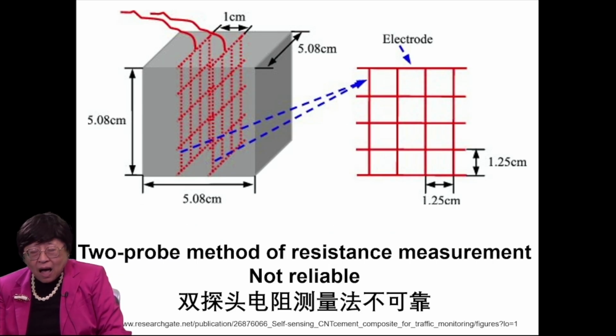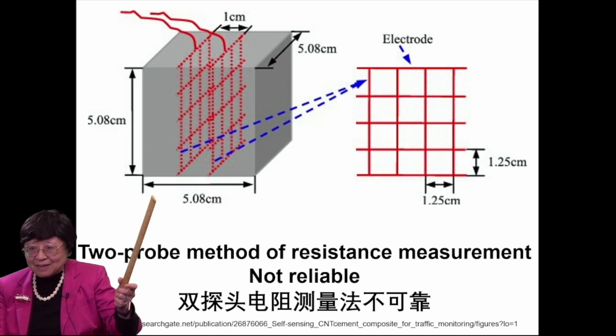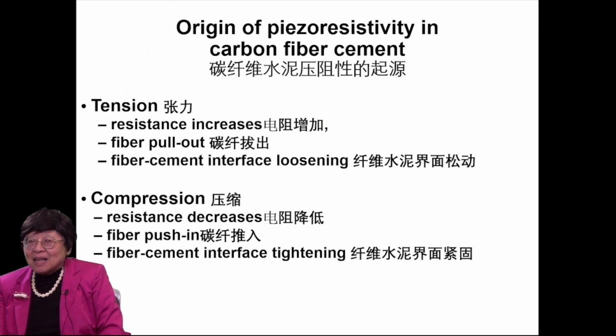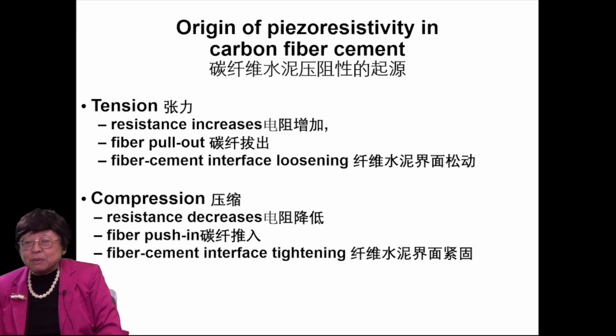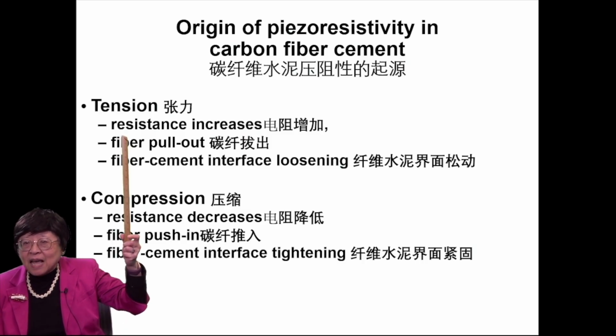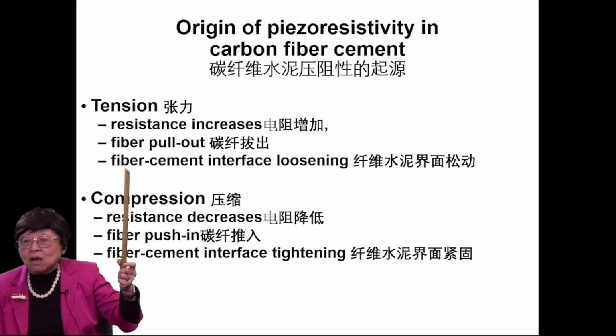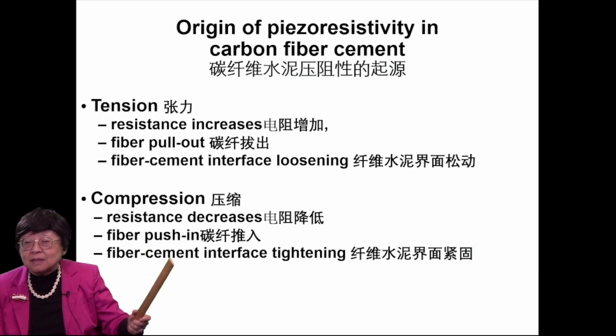However, a lot of published work has used the 2-probe method. The origin of the piezoresistivity in carbon fiber cement: for tension, the resistance increases, and that's because of fiber pullout, thus causing the fiber-cement interface loosening. Under compression, the resistance decreases because of fiber push-in and the consequent fiber-cement interface tightening.